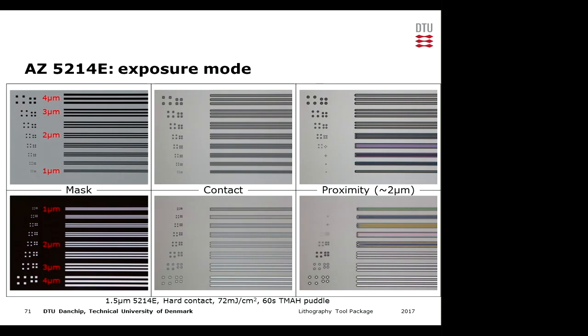And you can see the smaller ones completely disappear. And the bigger ones just have some funny corner effects, and some of them are rounded or something like that. But other than that, the big ones are not affected so much. So what we see with the proximity effect here, in this case, I'm using a proximity gap which is comparable to the thickness of the film.